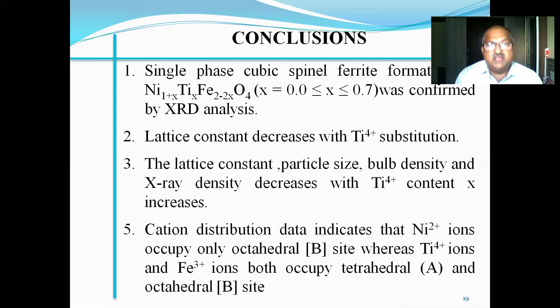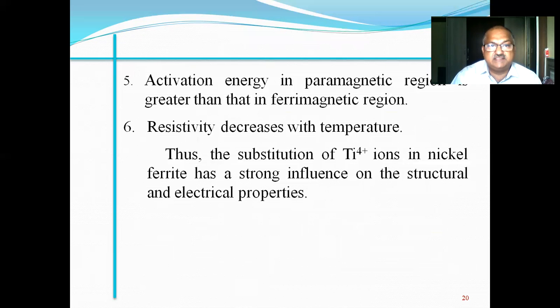increases. Cation distribution data indicate that Ni2+ ions occupy octahedral B sites, whereas Ti4+ ions and Fe3+ ions both occupy tetrahedral A and octahedral B sites. Activation energy in the paramagnetic region is greater than that of the ferrimagnetic region. Resistivity decreases with temperature. Thus, the substitution of Ti4+ ions in nickel ferrite has a strong influence on structural